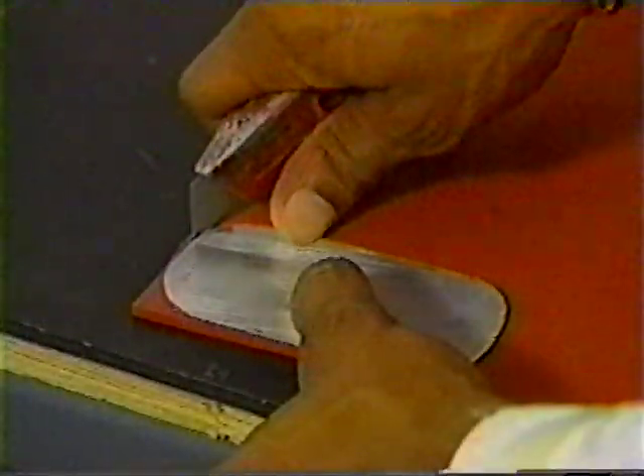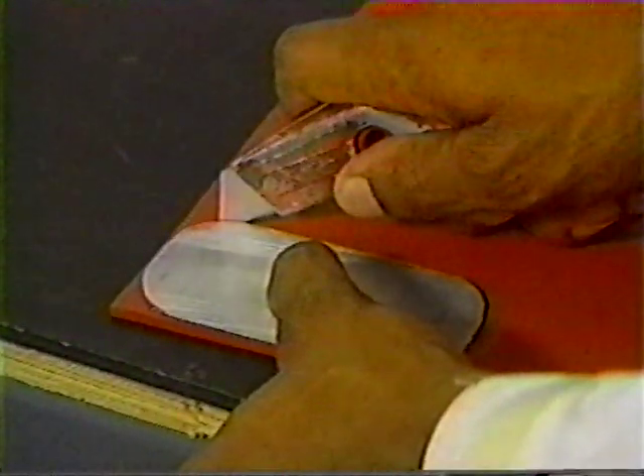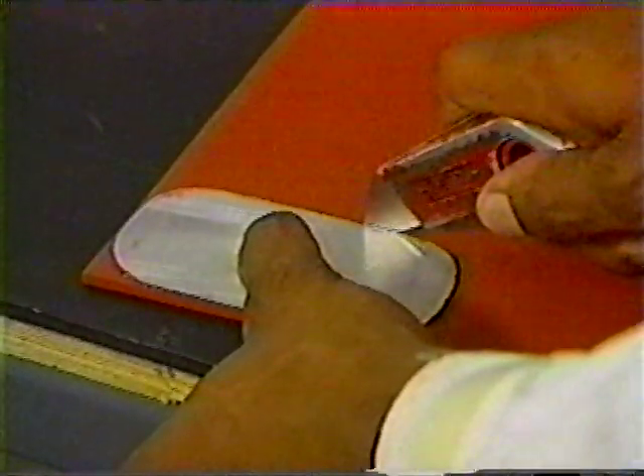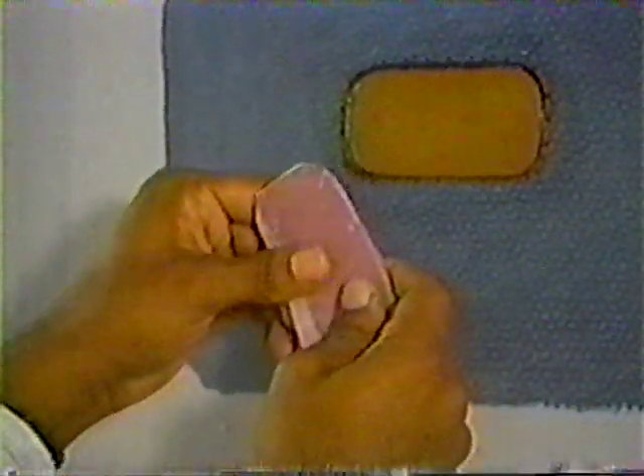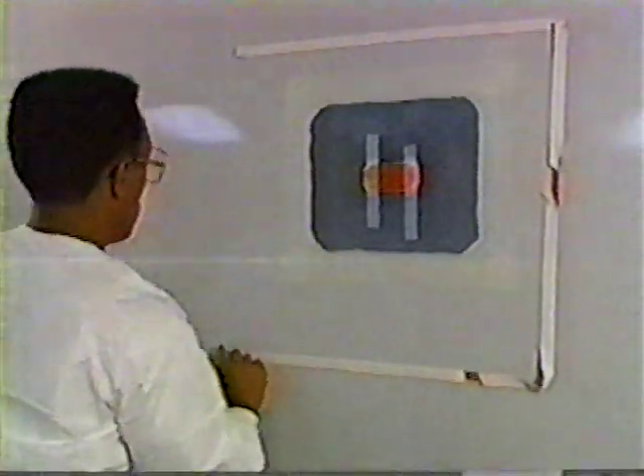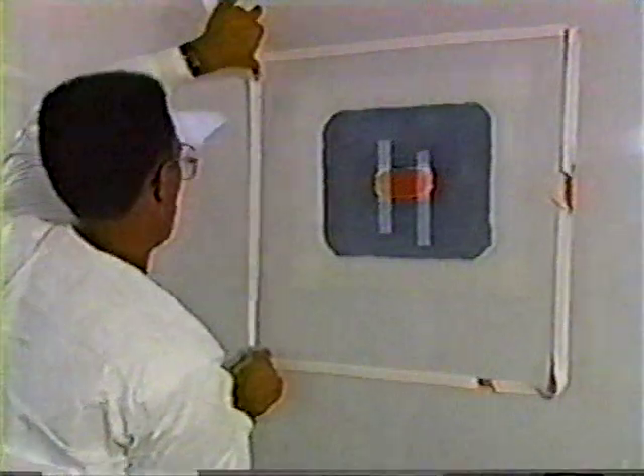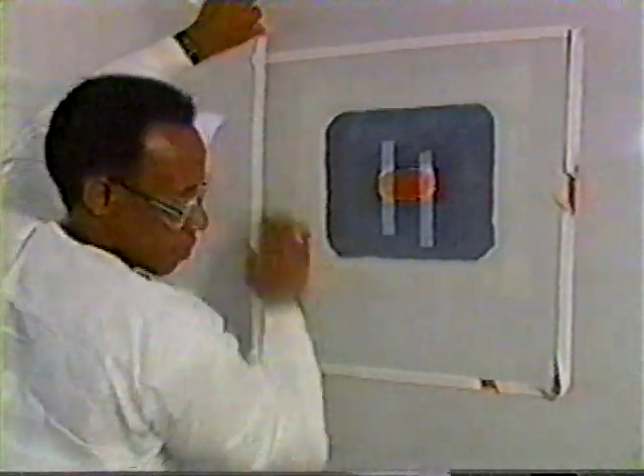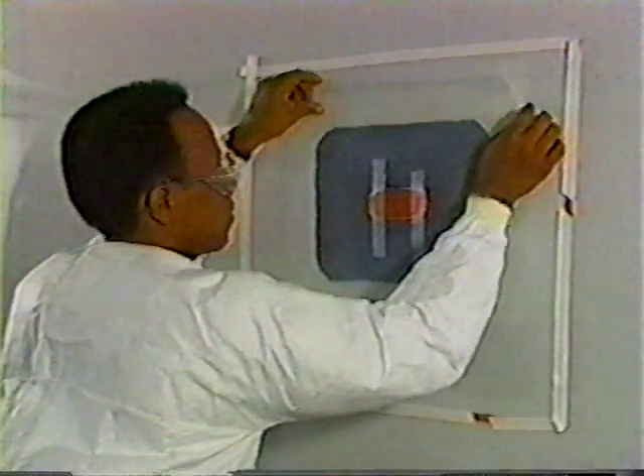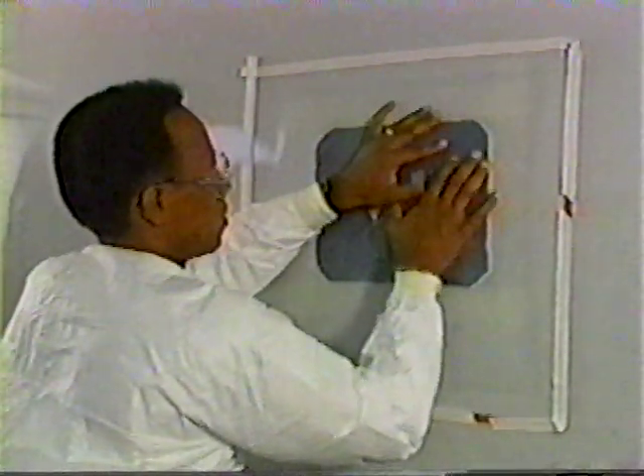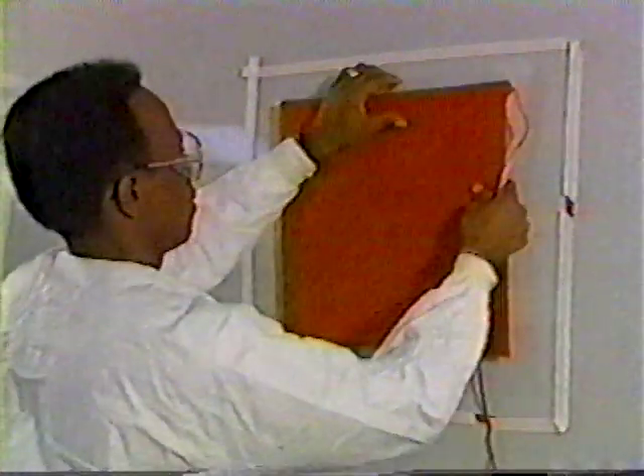One method of accomplishing this is to cut one or more rubber sheets, the exact dimensions of the cap, and thick enough to be slightly above the surface of the outer skin. After covering the rubber material with Teflon tape, place the tape side down over the cap. Then, secure the cap into place. Following this, position a strip of sealant tape around the repair area, at least 2 inches beyond the area of the heating blanket. Then, place a sheet of non-porous parting film over the repair, followed by the heating blanket.